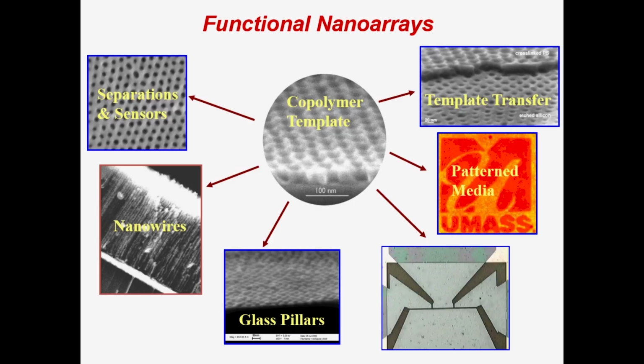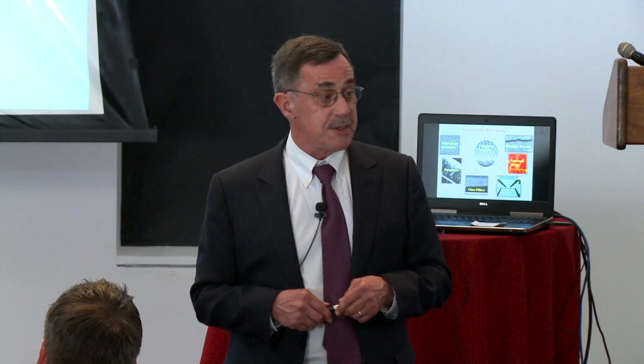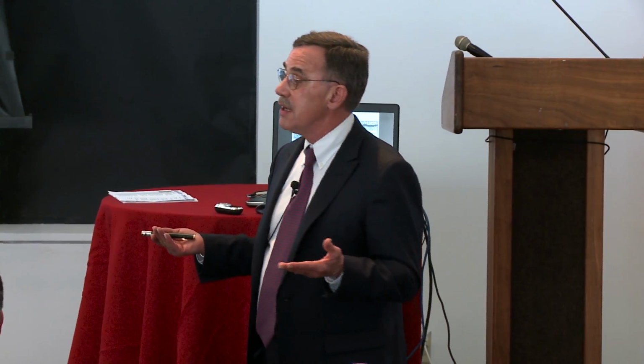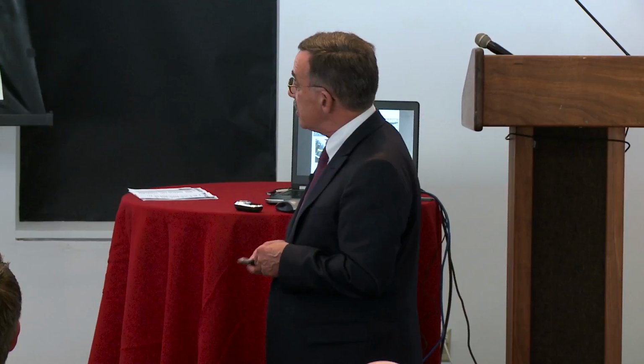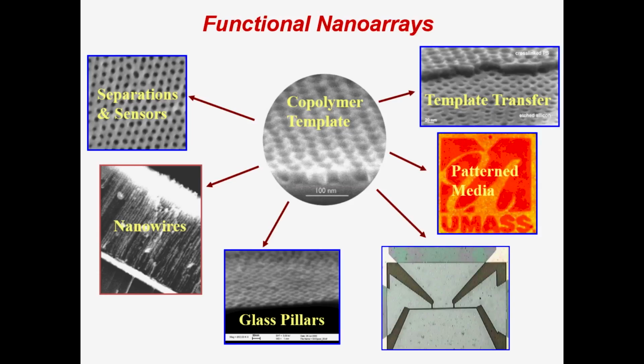So this basically is a membrane, a polystyrene matrix with holes. The holes in these are commensurate with the size of these domains, and in this particular case, it's 15 nanometers. So here I have a polymer film that has 15 nanometer holes that are separated center to center by about 30 nanometers. It's really a high areal density of holes. You can use that as a filter, and I can filter viruses with this. I can filter virus particles which have size scales that are 10, 15, 20 nanometers, and I can use this as a separations media.